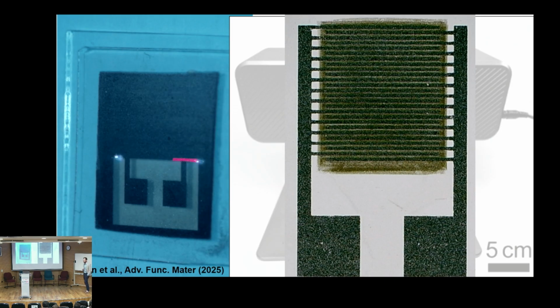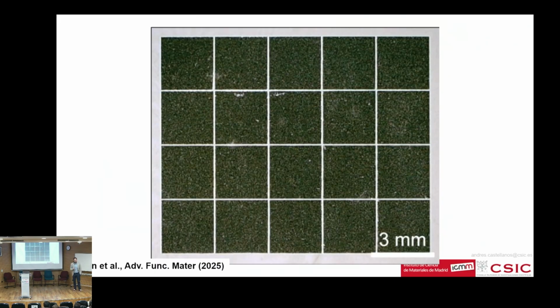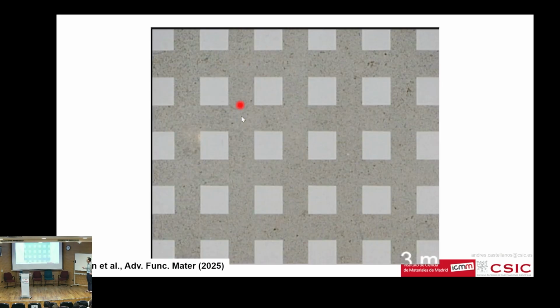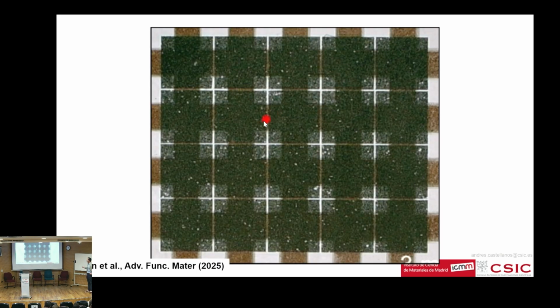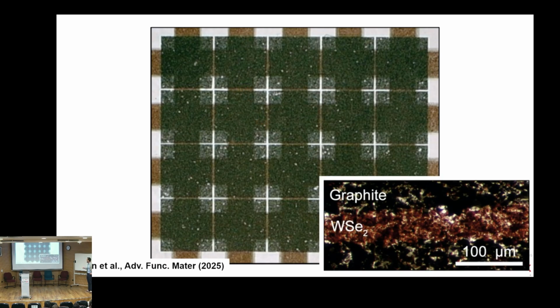Okay? So we started to think about what kind of more complex devices we can do with, let's say, low effort. What can we afford in our group to do that is a little bit more complex than just a photodetector? So we did these graphite electrodes and tungsten diselenide grids, stamping the tungsten diselenide on top. And if you take a look at one of these regions here, basically you have a graphite electrode, tungsten diselenide transistor, a graphite electrode. So we have an array of photodetectors. So we have a little camera here, okay?